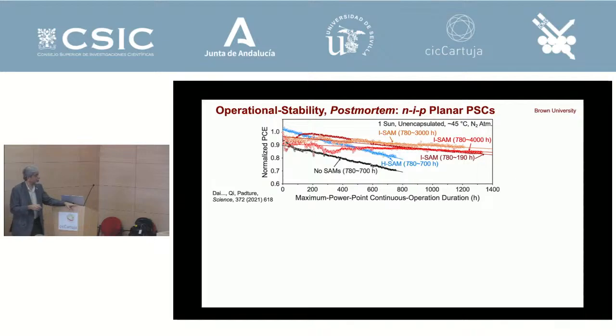All right, so this is what is called stability. We basically use the maximum power point. It's a very severe test because normally solar cells don't operate continuously for thousands of hours, right? They work for 12 hours, sometimes 14 hours in summer, and then it becomes dark and they can relax. But this is a very severe test, and what it shows is that if you don't put the SAMs, if you don't toughen the interface, then the T80, which means loss of efficiency by 20%, so it retains 80% of its efficiency, that time is about 700 hours. And when you put the SAMs, these are 3 different devices, it can go up to 4,000 hours, right?